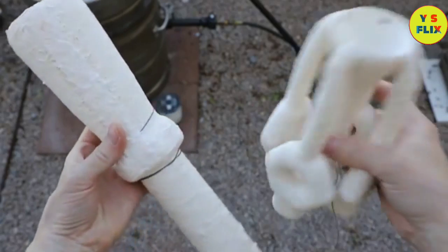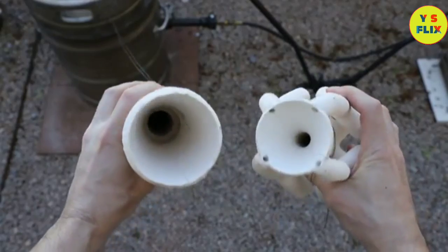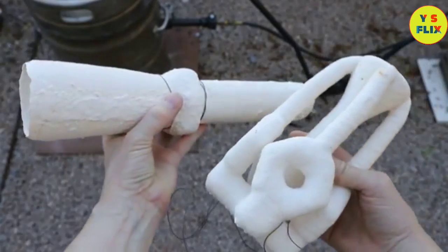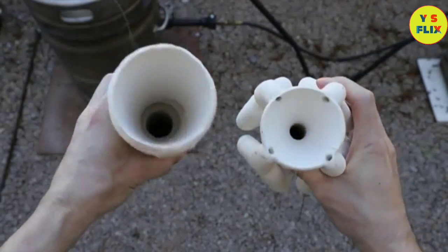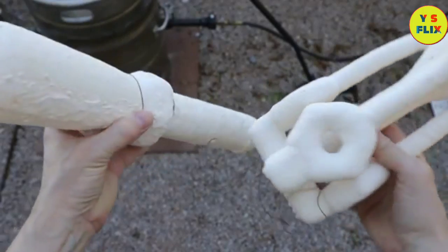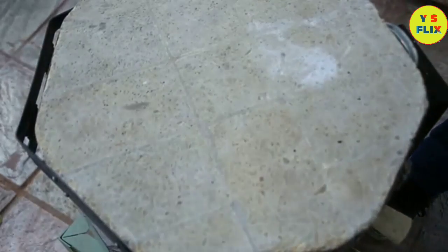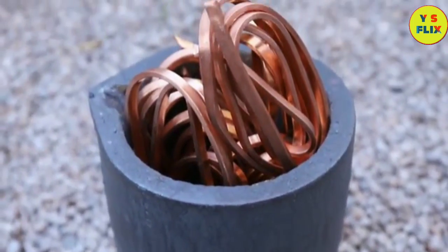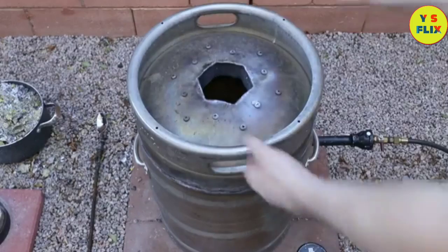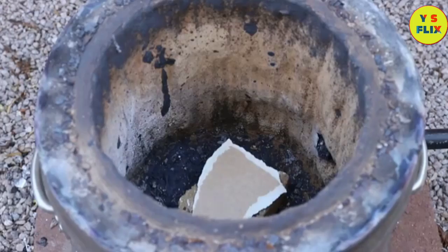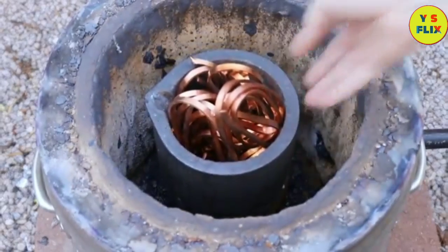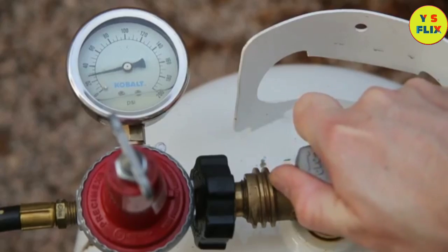The next day, I inspected the shells and I was happy to see that none of them had cracked substantially. At this point, the shells were almost ready to be filled with metal. They just needed to be preheated to about 1000 degrees Fahrenheit, so I placed them back into the kiln for a couple hours. The nuts were cast in bronze, consisting of 90% copper and 10% tin.